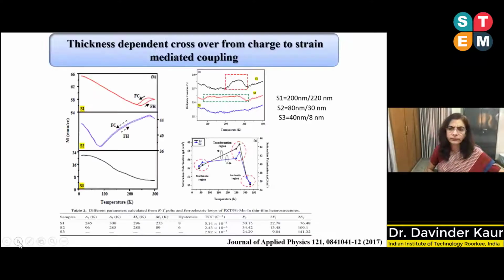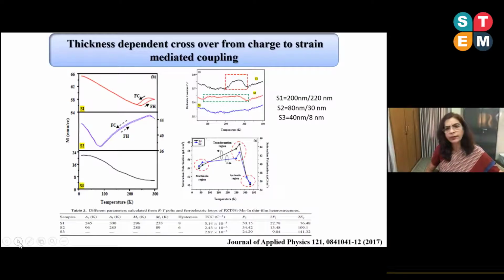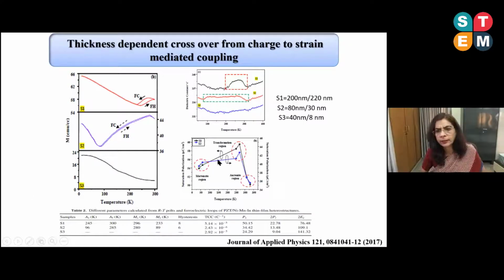Then we also tried to see the thickness dependent crossover from the change in the nature of the coupling in these heterostructures. For that, many heterostructures were made, and I'm showing the result for three of them, in which the FM layer was 200 nanometers, and the FM and FE layers were of various thicknesses.